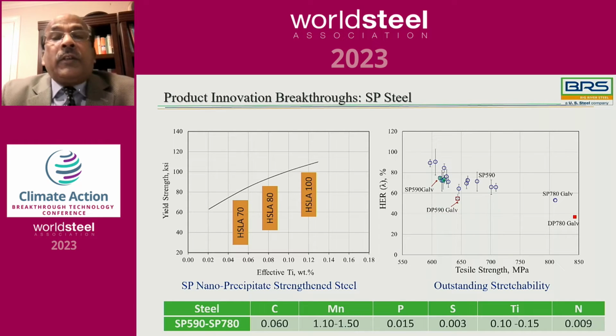These plots show, on the left-hand side, the yield strength as a function of effective titanium content, keeping carbon, manganese, and all other elements the same. Just by varying the total titanium content in the steel, various steels with various tensile strength levels can be made, like HSLA 70, HSLA 80, HSLA 100.